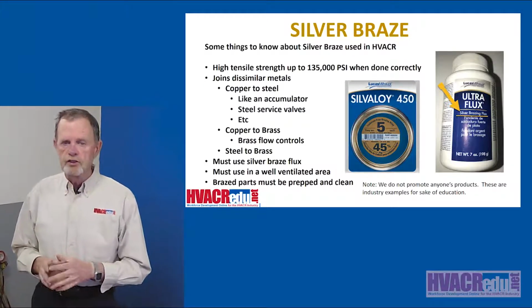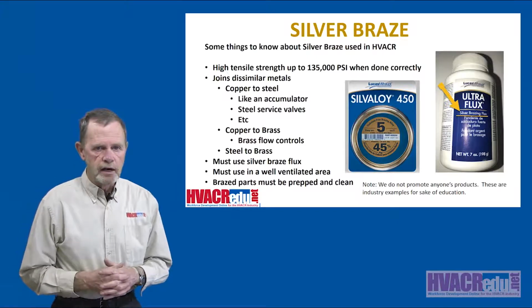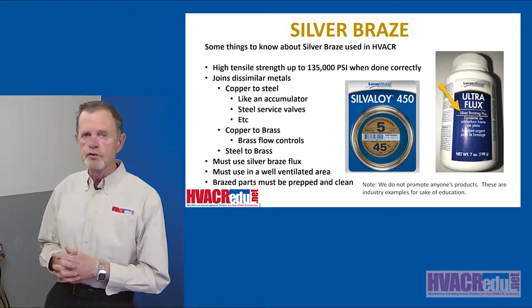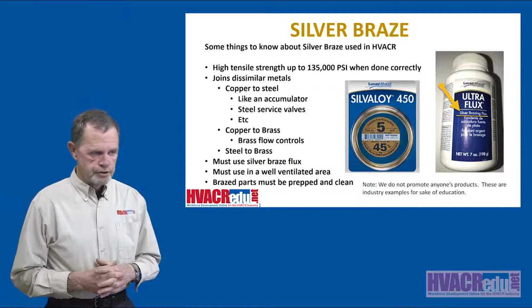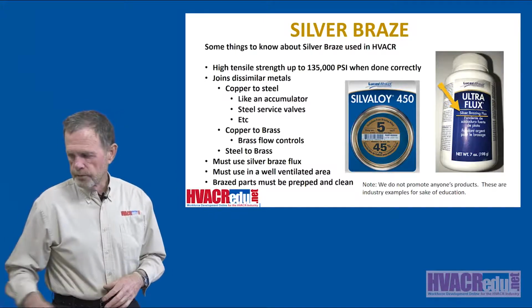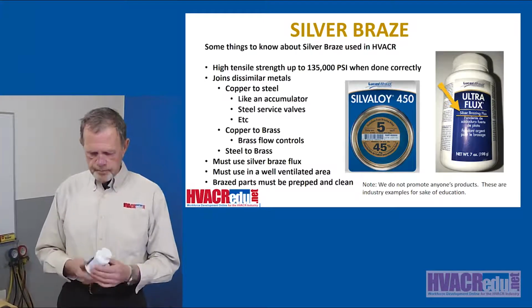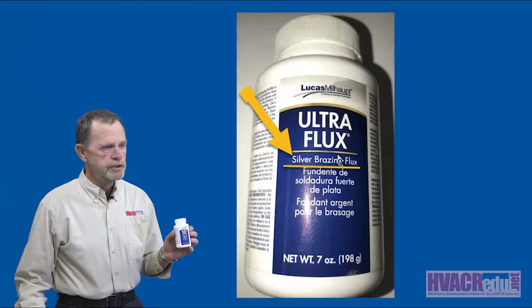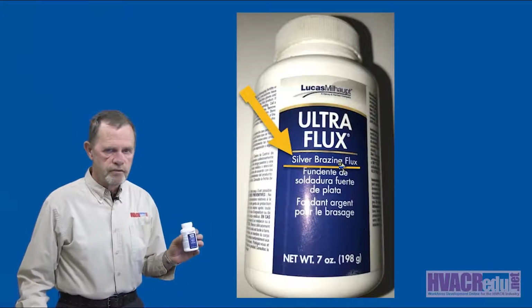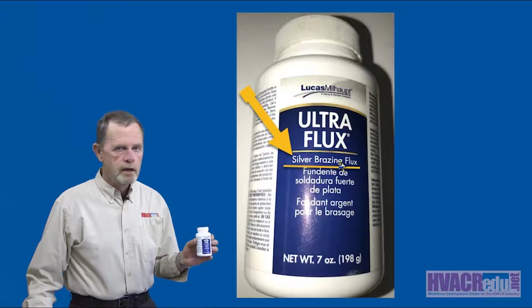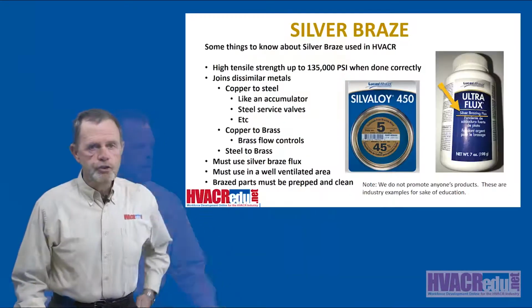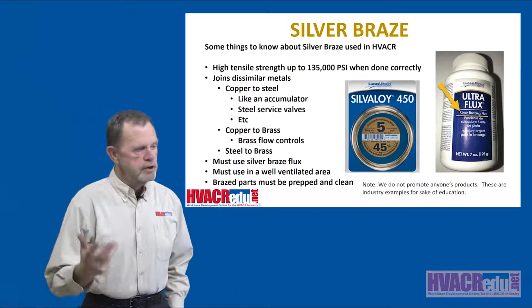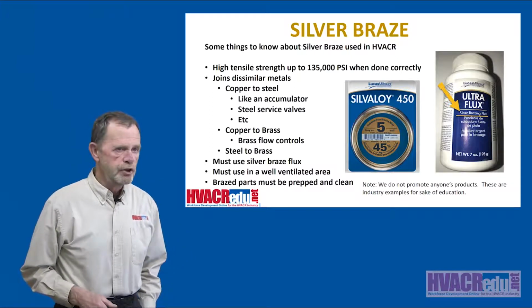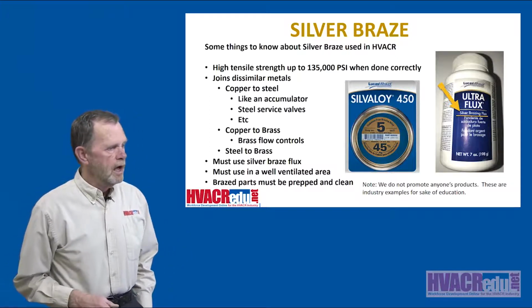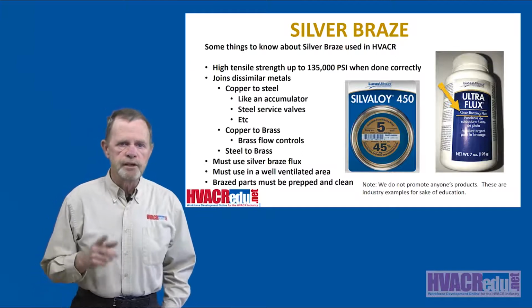Now, one thing about silver braze, unlike Silphos, where you don't have to use any flux at all, with silver braze you have to use flux. And in addition to that, it has to say, as a little picture here says, a silver brazing flux. Otherwise, it's not going to work. Must use in a well-ventilated area. Well, that's pretty consistent with just about any kind of brazing, soldering kind of stuff. And braze parts must be prepped and clean.